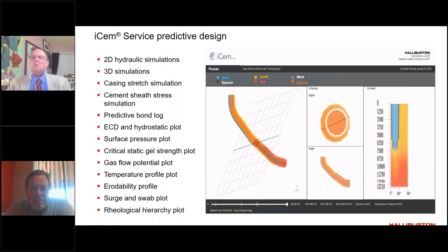We're able to do casing stretch simulations on some of the wells drilled nowadays. They are much longer and much hotter, and we can see pipe stretch on a 25,000 foot 7-inch casing at 260 degrees. We can see the pipe stretching up to about 80 foot. So if the pipe stretches during the cement job up to 80 foot and buries itself in the end of the well, that could mean the end of the cement job prematurely.